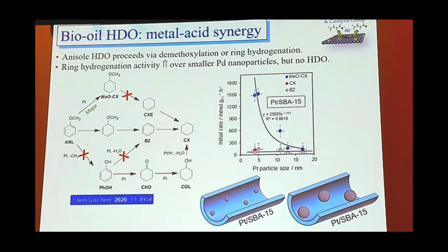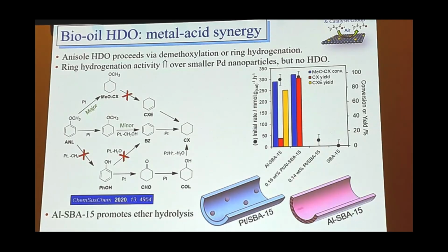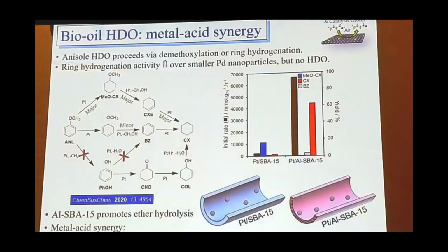So we know that acids can help C-O cleavage. So what happens if you add an acid to that system? Well, if you put, for example, aluminum SBA-15 in with the methoxycyclohexane, it will actually cleave it to give you cyclohexene. So once we're actually going to the next step, if we run our hydrogenation catalyst, we'll be able to get all the way through to cyclohexane. So if we work with small metal nanoparticles that are optimal for hydrogenation, platinum SBA-15, or platinum Al-SBA-15, now start to get very clean yields of the fully deoxygenated product. And when you compare side by side the neutral and the acidic supported system, you can see that you get a huge promotional effect in terms of initial rate and also yield of your deoxygenation product.